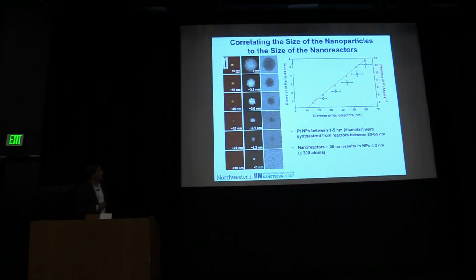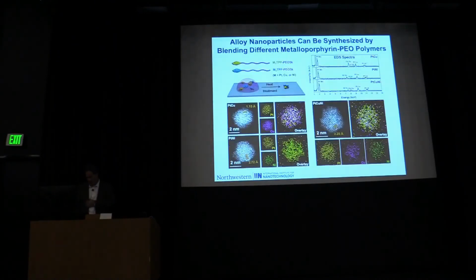And you can see that exactly what happens here, where we're dialing in, and these are really tiny reactors now, 60 nanometers going down to less than 20 nanometers. If you look at this, we can synthesize particles from 1 to 5 nanometers. So when we're less than a 30 nanometer diameter nanoreactor, we can make sub 2 nanometer particles. We're getting down to a countable number of atoms.